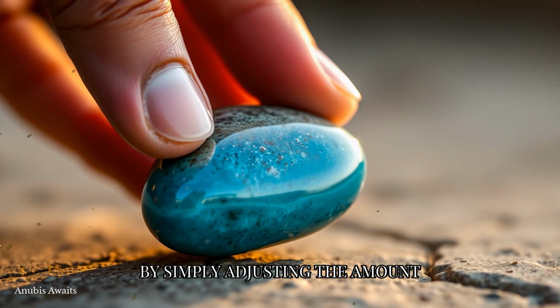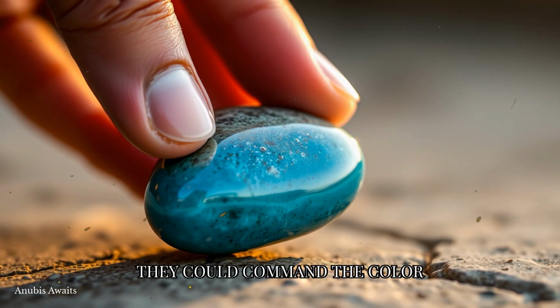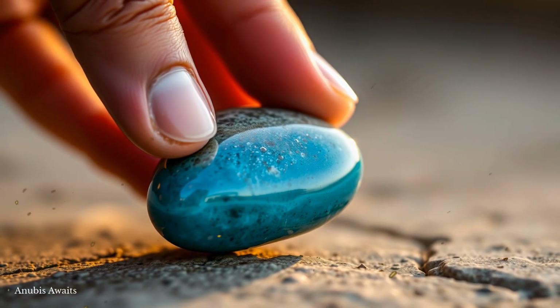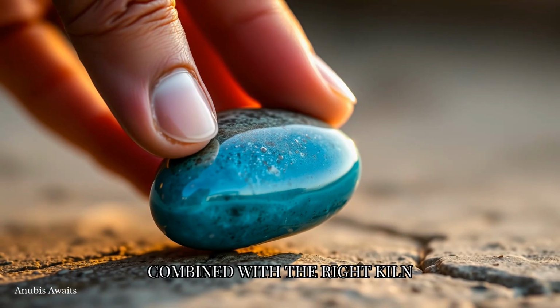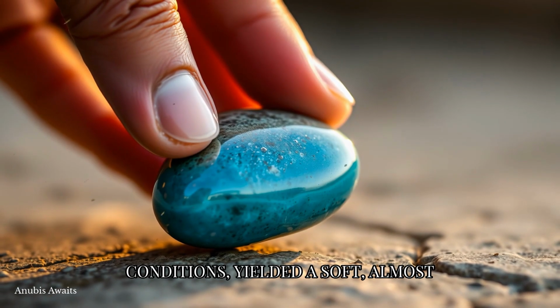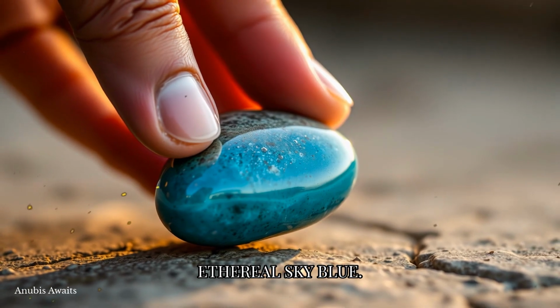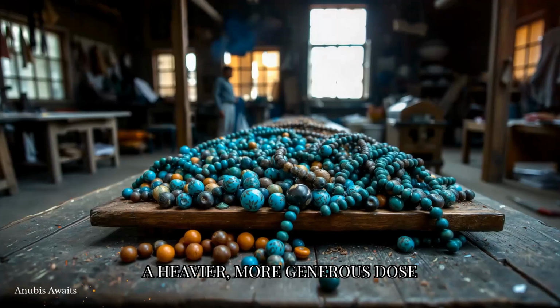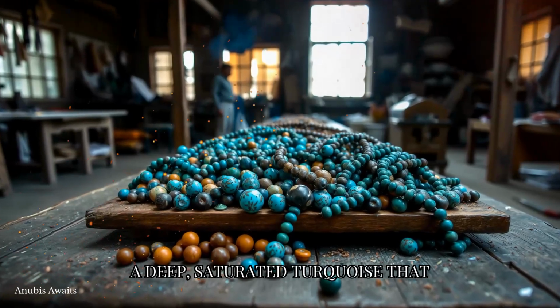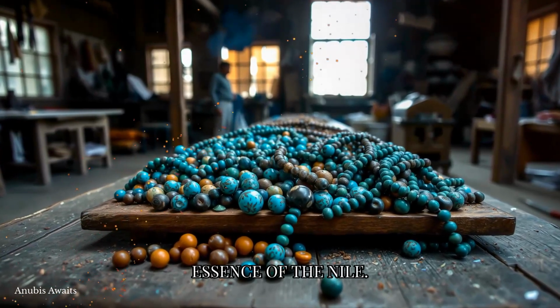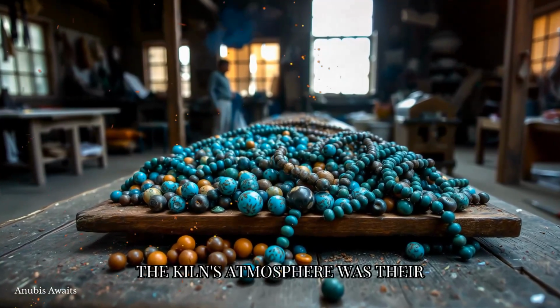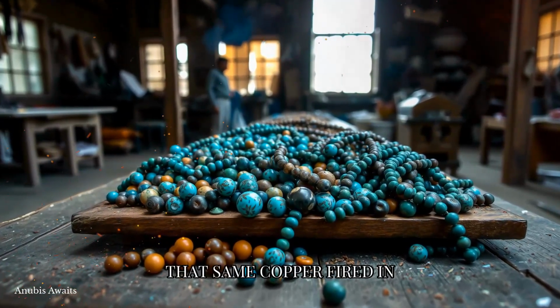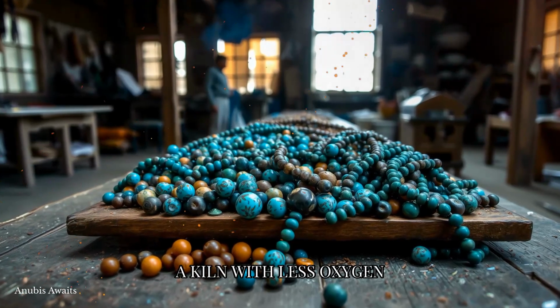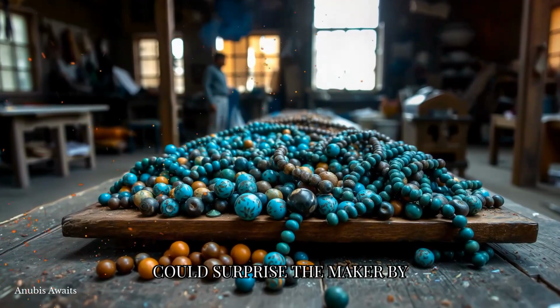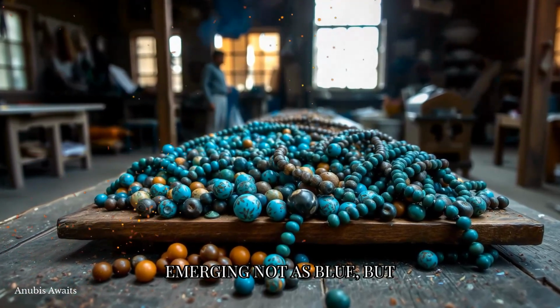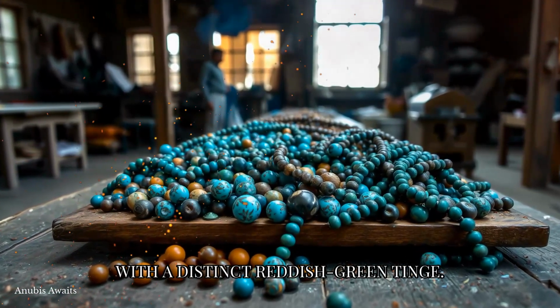By simply adjusting the amount of copper in the mixture, they could command the color to shift. A smaller amount of copper, combined with the right kiln conditions, yielded a soft, almost ethereal sky blue. A heavier, more generous dose of the mineral would produce a deep, saturated turquoise that seemed to hold the very essence of the Nile. The kiln's atmosphere was their final brushstroke. That same copper, fired in a kiln with less oxygen, could surprise the maker by emerging not as blue, but with a distinct, reddish-green tinge.